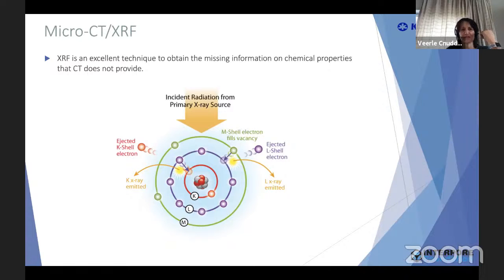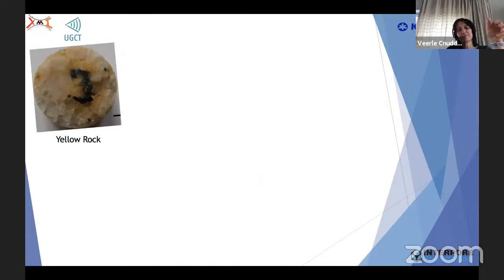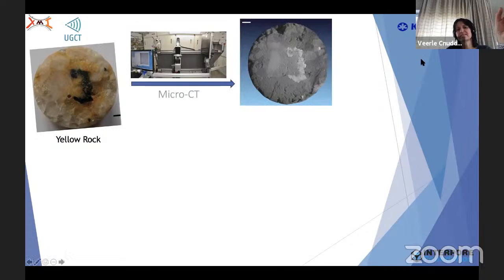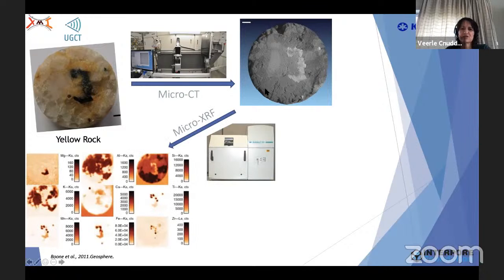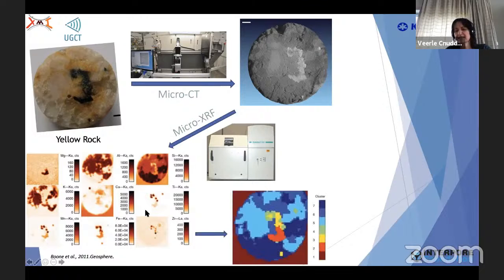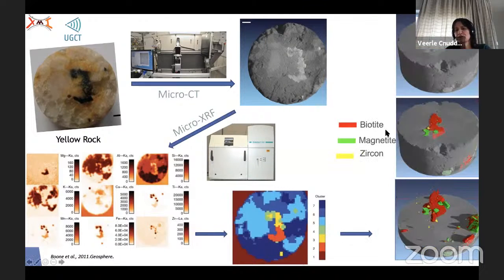So what we did in the past was take a sample, in this case a yellow rock, and scan it with CT. We see different gray values related to differences in average atomic number and density. Then this surface was put in another system to do micro XRF, giving us mapping of all the elements. By cluster analysis we identified the minerals, biotite, magnetite, and zircon, and matched this signal with the gray values in our CT image to estimate the distribution inside the entire volume.